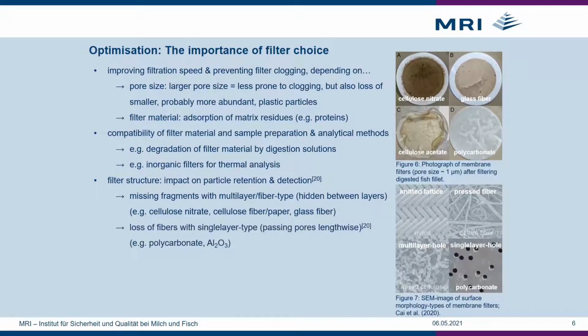In contrast, single-layer type filters have a smooth surface with pores of a defined size, which shows a good performance for retaining fragments, but may also lead to a loss of fibers that can pass the pores lengthwise.